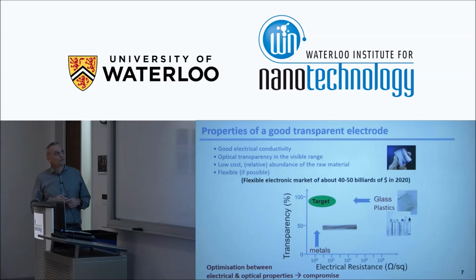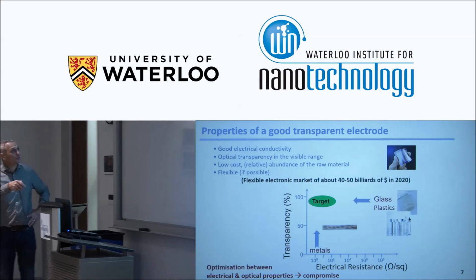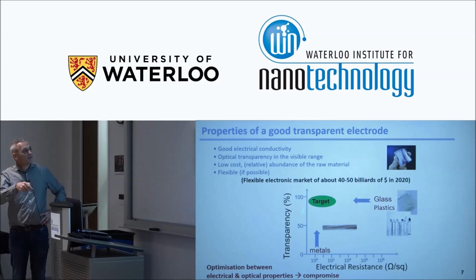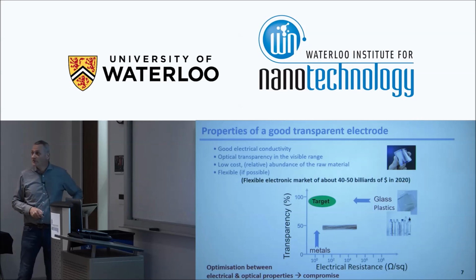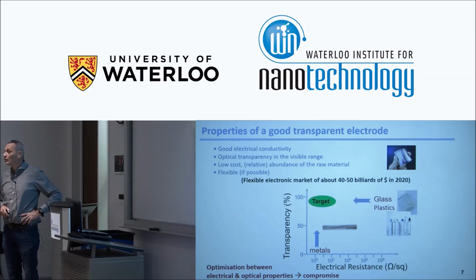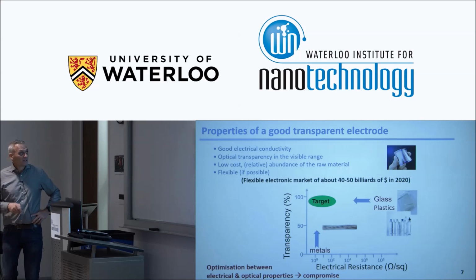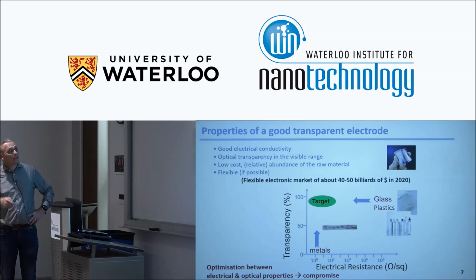So one way to show the properties of a transparent electrode is often to put here in the y-axis the transparency in linear scale, versus electrical sheet resistance for a thin layer, for example, in log scale. And the target is here. We are happy when we have transparency of about 90% and a sheet resistance of about 10 or 20 ohm per square. This is the target.